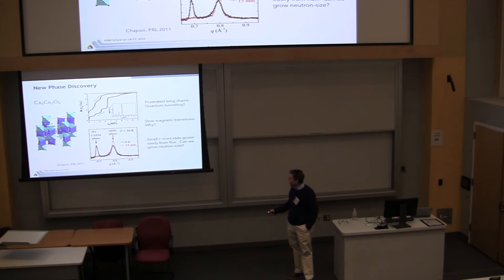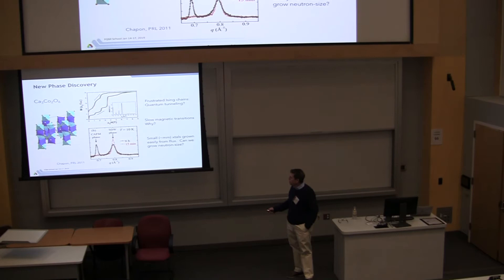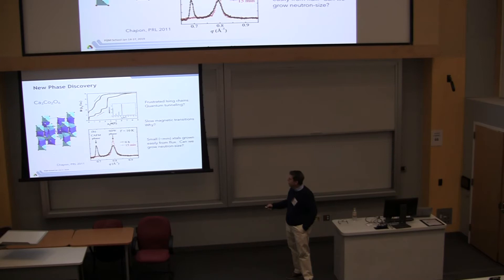You might be able to find a good flux to grow it, but it's pretty tough, narrow. So what's better if you could just make this a congruently melting compound? And it turns out that using these calculations, they show that at, I don't remember, is it labeled on here? It isn't labeled on here, but maybe this is 50 or 100 bar or something. That phase diagram changes completely. And so now you can see that the compound melts congruently into a liquid. It's a much better situation.